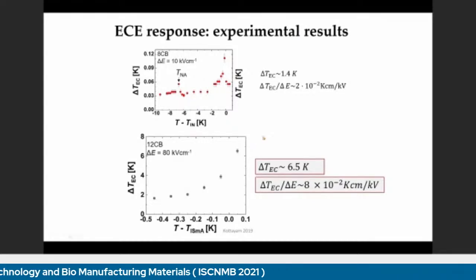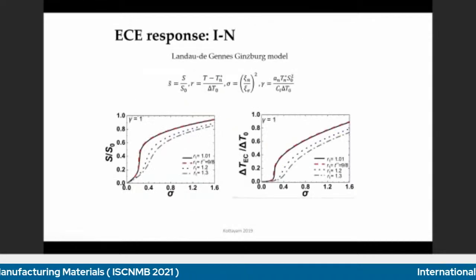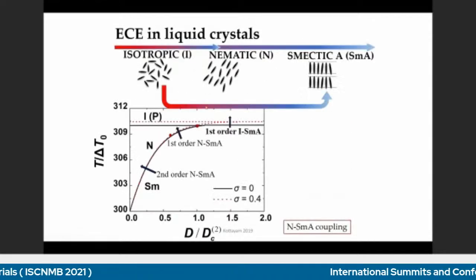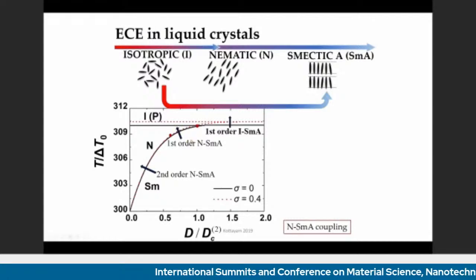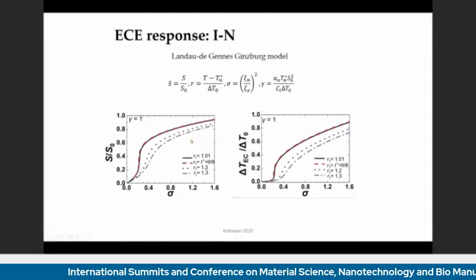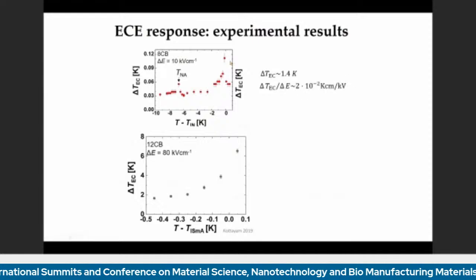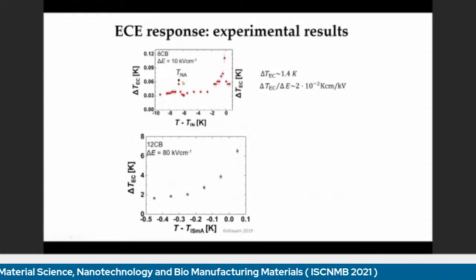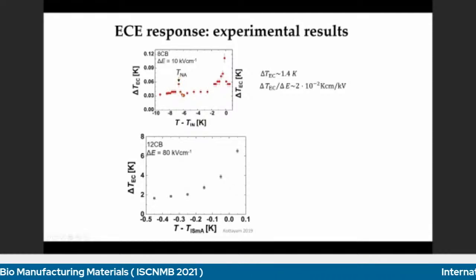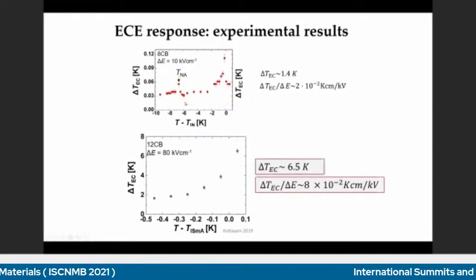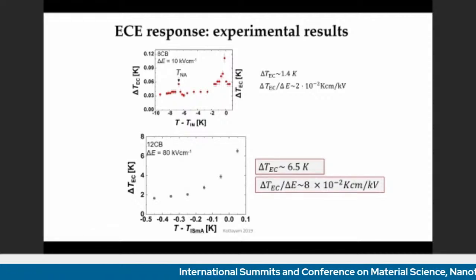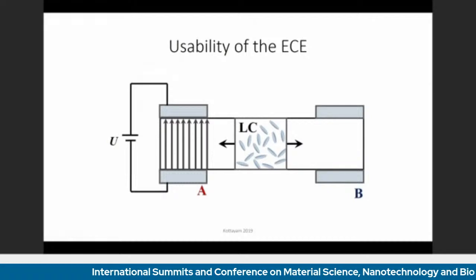So if we go a little back, here we see there is the second order transition and the first order transition. If we continue, we see that the first order transition from isotropic to nematic is here, and the second order from nematic to smectic is here. So this second order transition is much lower than according to our simulation.